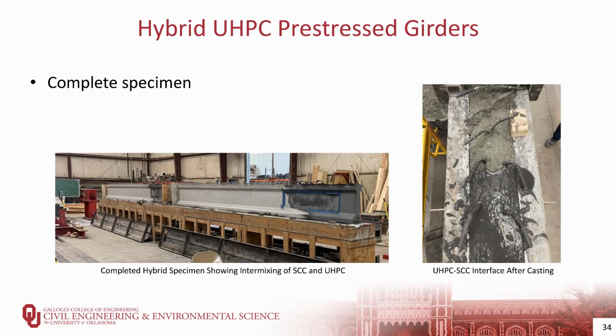Yeah, one concern that we mentioned at the beginning is that with these potentially having different shrinkage behavior, there's the possibility for that kind of a gap to open up, but we didn't see that on any of these specimens. And once we pre-stressed them, obviously we're putting a compression across that interface, but we didn't see a gap even before we pre-stressed them.